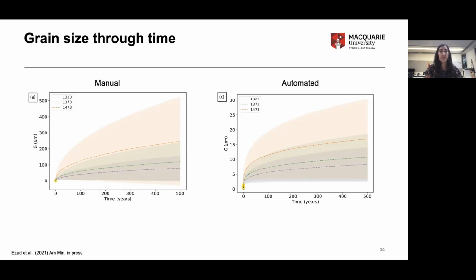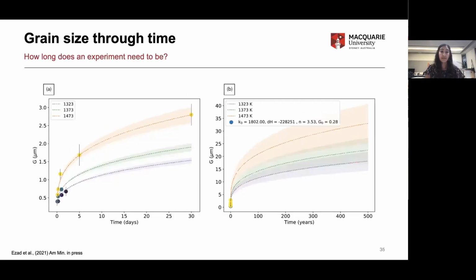To ensure that this wasn't just a problem with the experiments, I did some synthetic modeling to forward model this problem. I thought, well, how long does an experiment actually need to be before we can start to constrain geological time with our kinetics? I ran lots of forward models, and it became very obvious that an experimental duration of even 30 days wasn't long enough for me to collapse the confidence intervals for just a short period of 500 years.